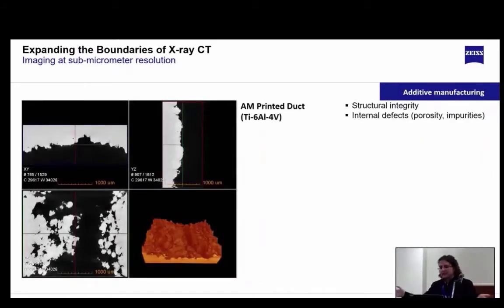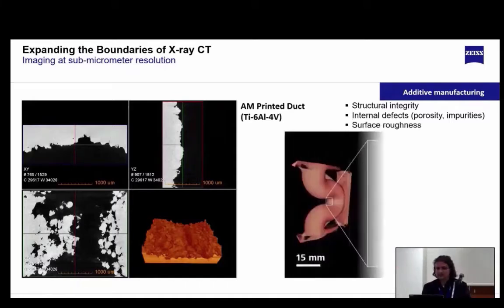And there are other applications, such as quality inspection of parts made by additive manufacturing. For example, without destroying the part, you can inspect at high resolution the structural integrity of the internal cavity, check for internal defects such as porosity, impurity, inclusions in the powder material, and do measurements such as surface roughness.